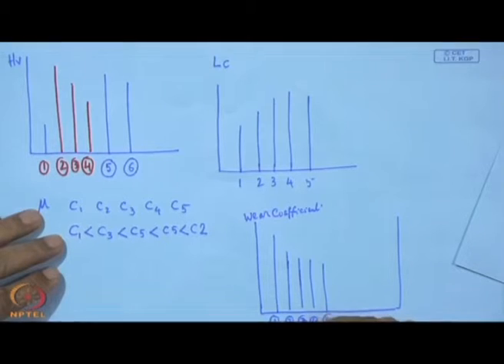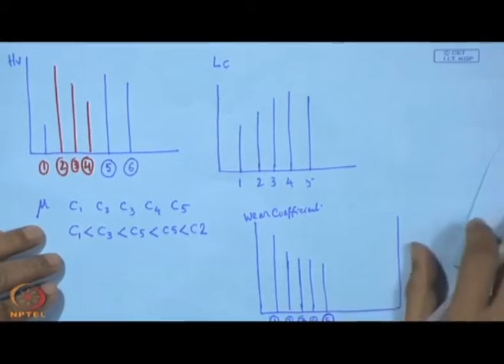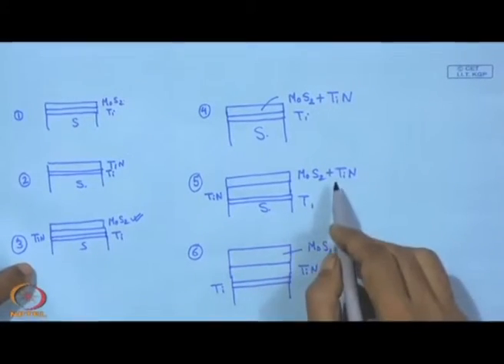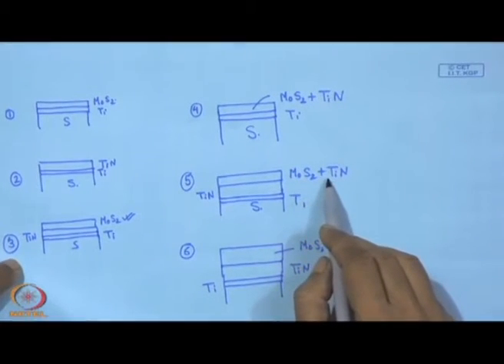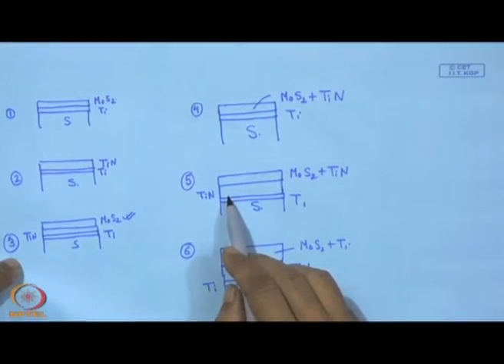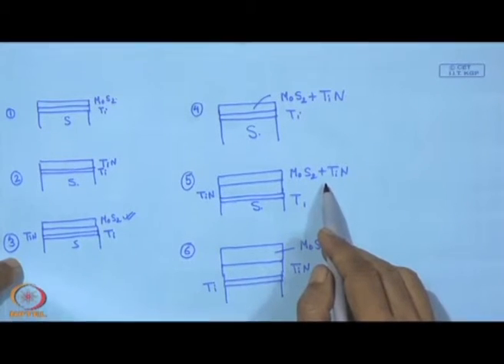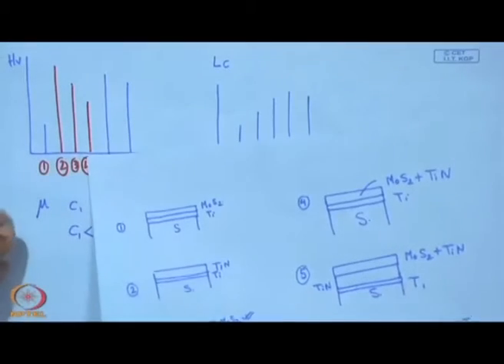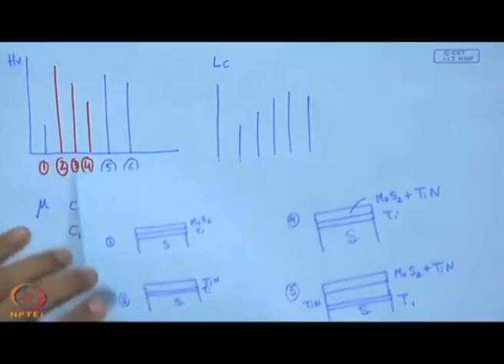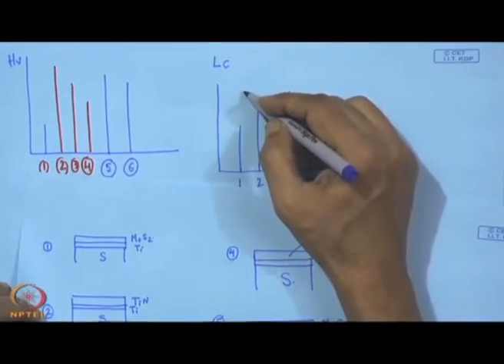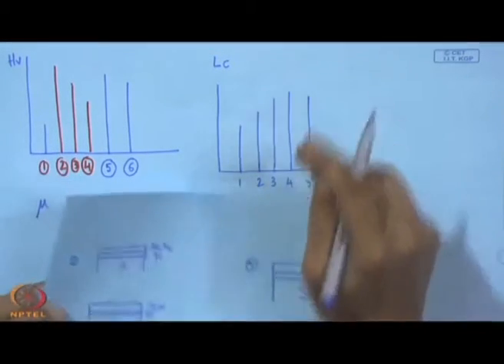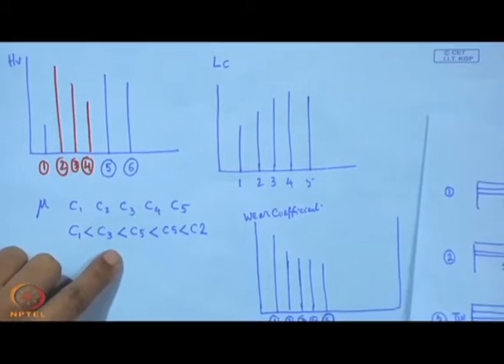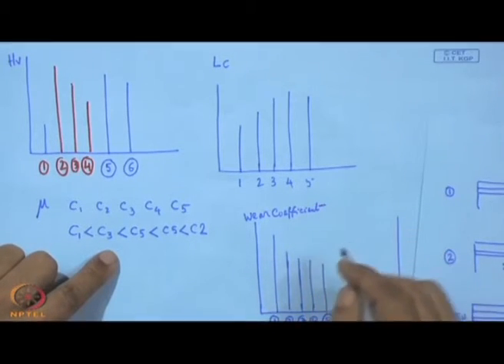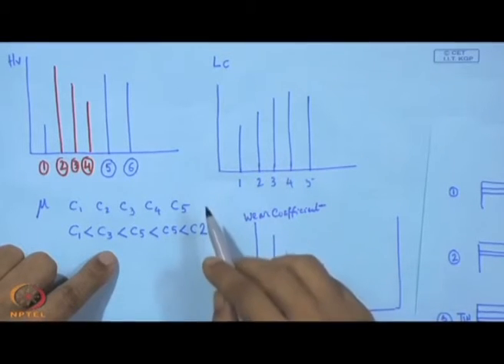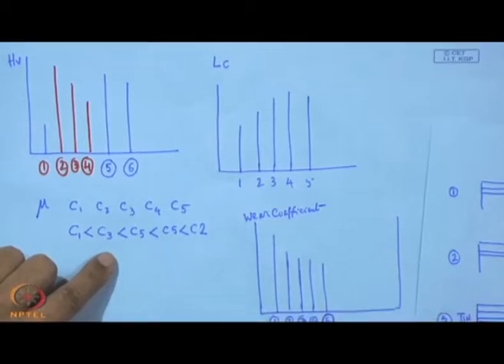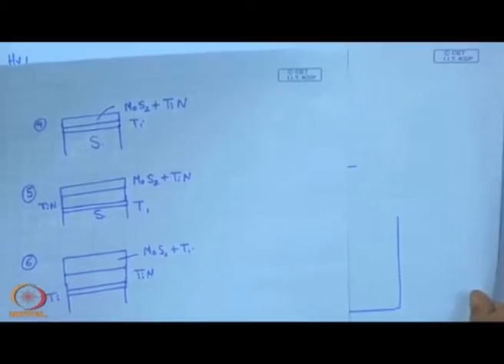So, from this point of view, we find that this fifth one, the architecture with MoS2 plus TiN with a support of TiN, gives one of the best values in consideration of hardness, number 1; adhesion with the substrate, number 2; the coefficient of friction, number 3; and the wear coefficient, number 4, that is, how much the wear is.